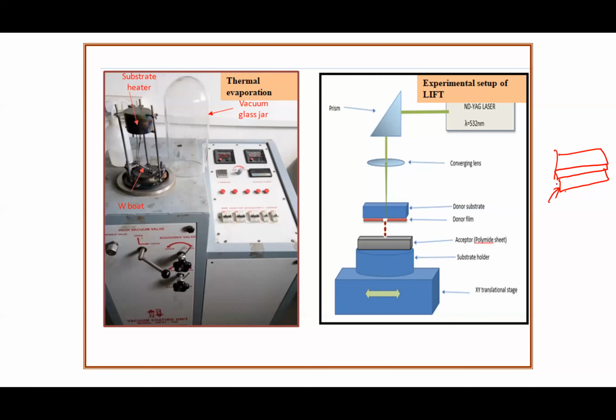So now you have the flexibility to create any kind of thin film material. For example, if I want to make nickel titanium, I can go for a nickel titanium sputtering target or thermal evaporation. I can coat it and then go for 3D printing. The second concept is that I can go for multiple layers. One might be nickel, another might be titanium, and here this is a sacrificial layer, so that the transfer will happen with respect to both on the surface. The third important concept is that this is a kind of maskless manufacturing, like how you go for die-less manufacturing.